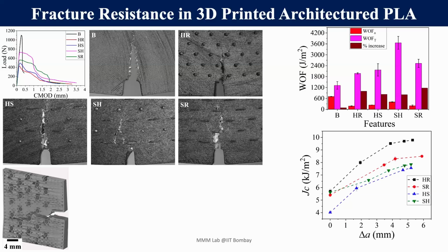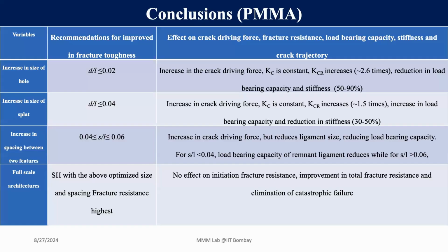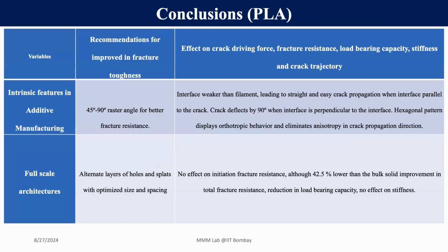And we saw the rising R curve for each and every architecture, and the simulation results also match the experimental results. So here are some recommendations for when you are designing the architecture about the hole size and spacing between them. It is the linear elastic fracture mechanics of the PMMA, and this is about the PLA.